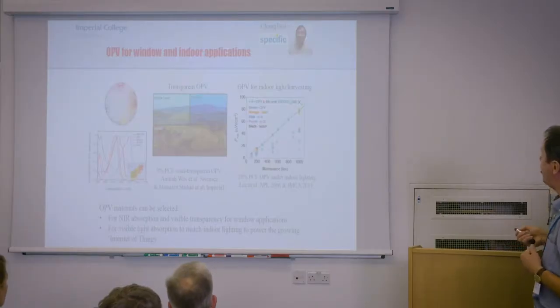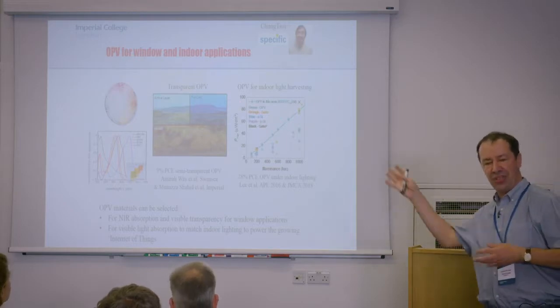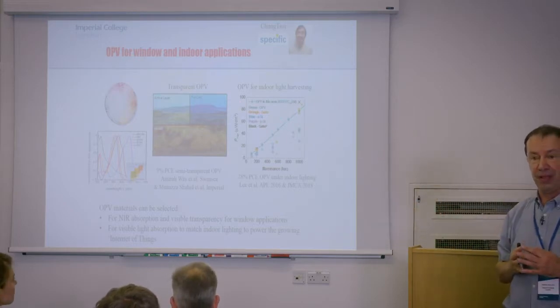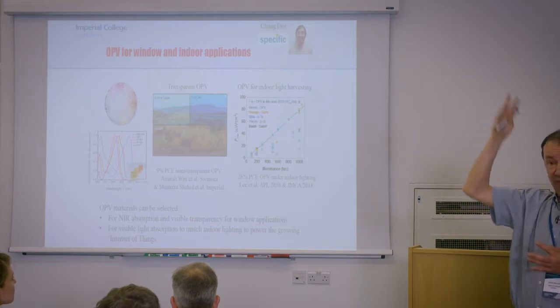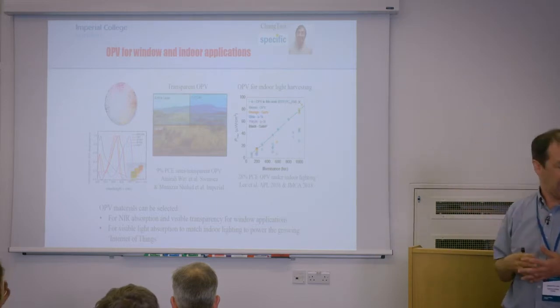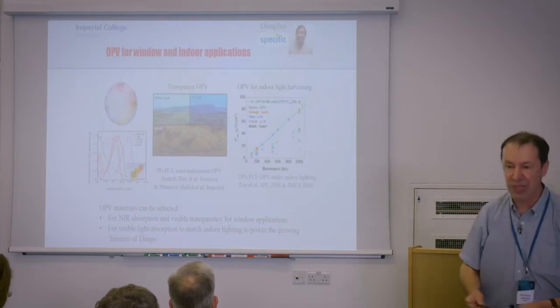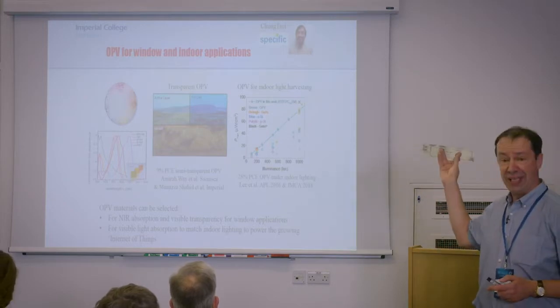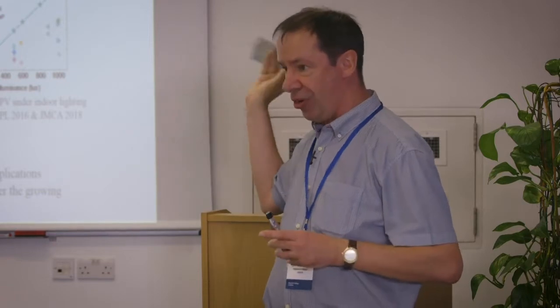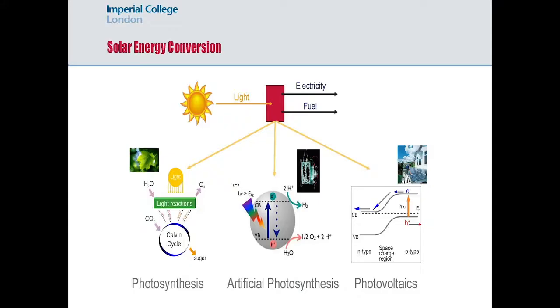Here's another example where you can tune it the other way. You can design solar cells where they only absorb the visible, so they only absorb indoor lighting and are rather bad at getting energy out of the sun. In this case, we can now get to efficiencies of flexible cells which are significantly more than silicon or even gallium arsenide for indoor applications. That's interesting. That's not going to save the planet, but it's interesting for energy harvesting, for the Internet of Things, and our move towards energy harvesting in buildings.